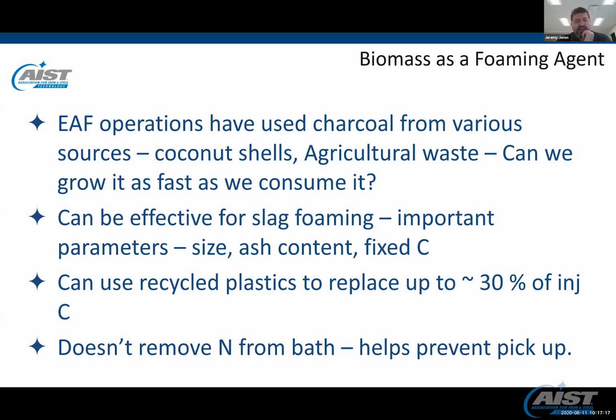There's a lot of work done at University of New South Wales on recycled plastics, and they found they could substitute about 30% of the injection carbon with plastics fairly effectively. But the issue is that the plastics break down much more rapidly than carbon does. And so you're limited as to how much you can use because you get a surge of gas generated.